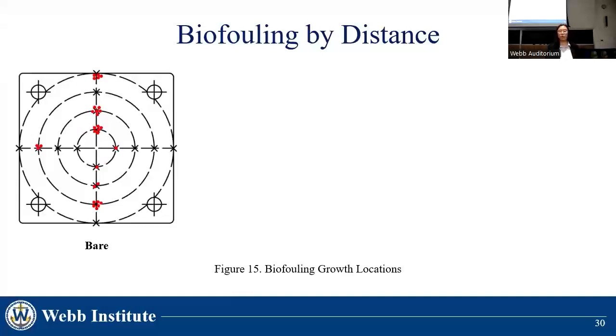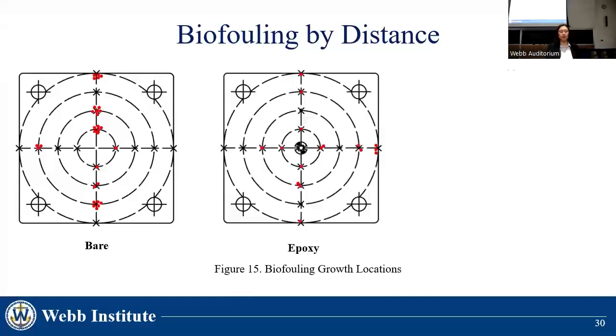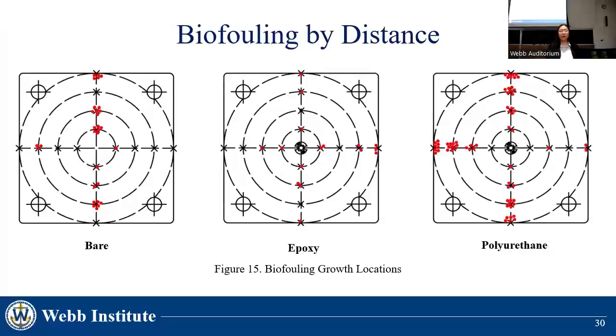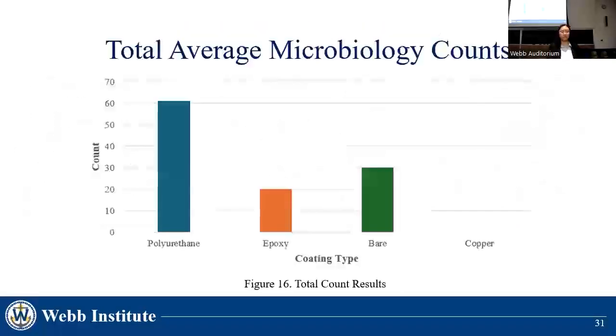On the left, you can see the average results of the 2 bare plates. In the middle is the epoxy plate. Finally, the right shows the polyurethane-coated plate. A total count of the average microbiology on each coating type may be seen above.